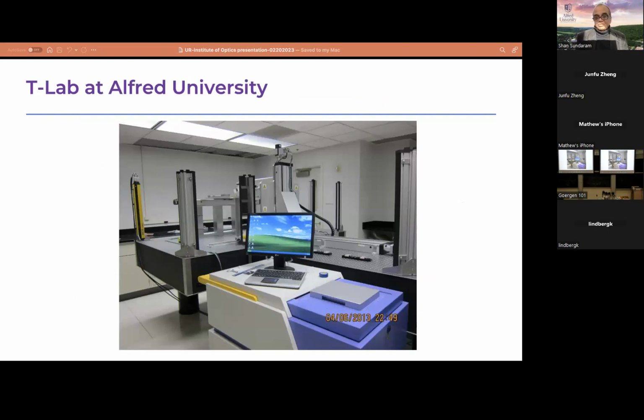This is the view of the instrument in our lab. You can see here, if you open this lid, that is where you can put your glass sample. Terahertz wave generation and detection both depend on a structured gallium arsenide semiconductor-based antenna approach. The terahertz waves are generated below this, inside the box, using an ultrafast pulse laser, and they're guided through the sample holder. Once you put your sample in, you let the terahertz wave pass through. In transmission mode, you can measure the properties and plot the real and imaginary parts of the optical or dielectric constant from the same data set.